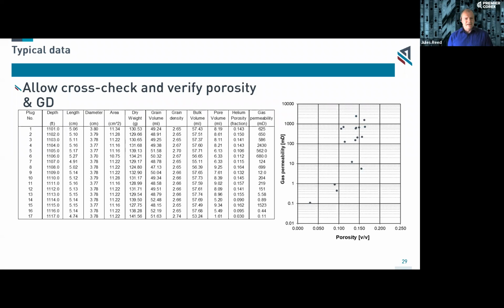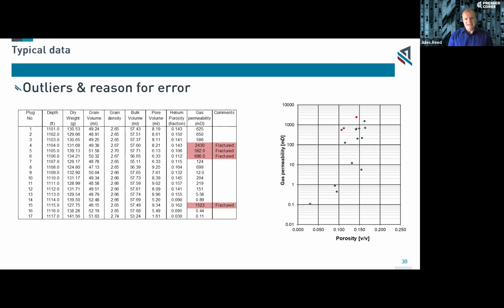Let's look at other variables, other metadata, and that is that four of these samples were fractured. Now, most laboratories would inform you of this, and they may not even report the fractured permeability. But those fractured permeabilities are those highest ones there on the plot. And we can begin to say, well, we don't believe these data because they're from fractured core. What we're measuring is the fracture, not the matrix.